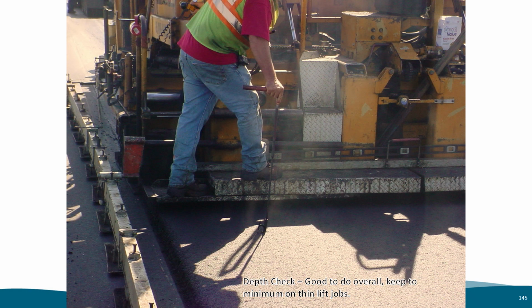Here the contractor's paver operator is doing a depth check of the asphalt mat before being rolled. Here they are using a steel bar with an adjustable marker, which is set to the desired thickness. As a laydown inspector, these depth checks are important to help you control the tons per station, so that the project lays the correct amount of asphalt and does not run too far over or under the required production tons.